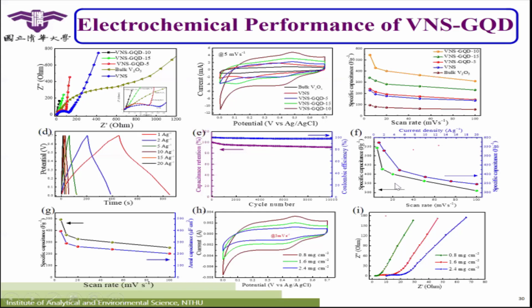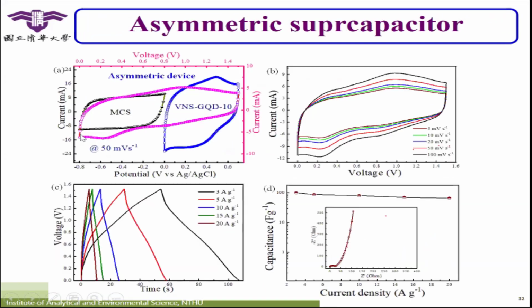And then when you merge them together, they can have very good efficiency here. So when you use the MCS as the negative electrode, you can see that their potential is negative. When you use the VNS with the GQD, where the weight percentage is 10, they can serve as the anode. So you can see that the potential is positive. So the behavior will be quite good here. And the potential will be from 0 to 1.5. So that's quite large.